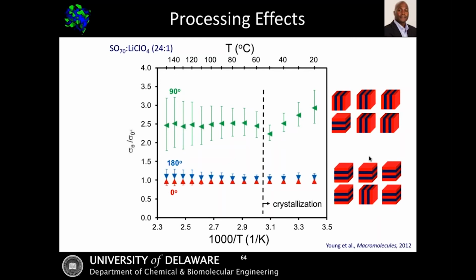Now, when we rotate each individual sample 90 degrees, and again do that in situ SAXS, we see that we now have samples with about 80% orientation in the conducting direction, and we actually increase the conductivity by a factor of about 2.5. Now you might say, is that just a feature of you cutting and manipulating the samples? But when we do 180 degrees, so we flip the samples again so they're back in their original geometry, we actually go back to baseline. So that's just a quick little story about how the fact that we've sandwiched and processed these materials puts inherent bias in that nanostructure and leads to differences in conductivity.